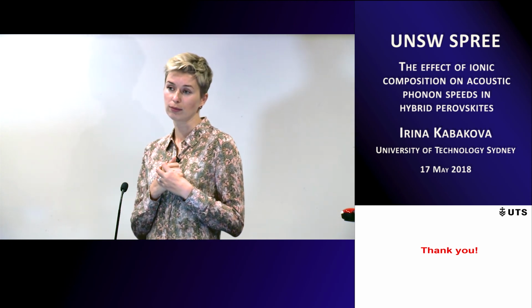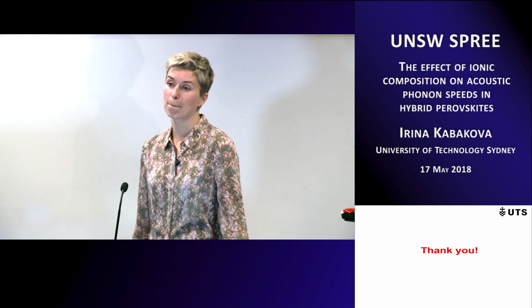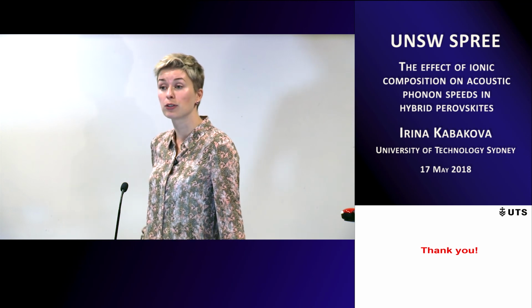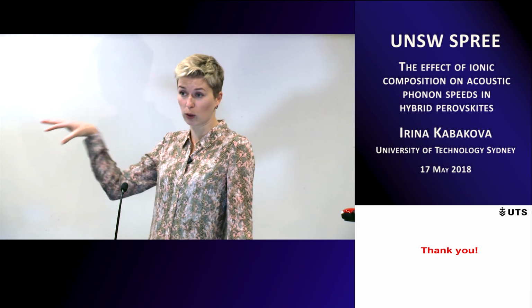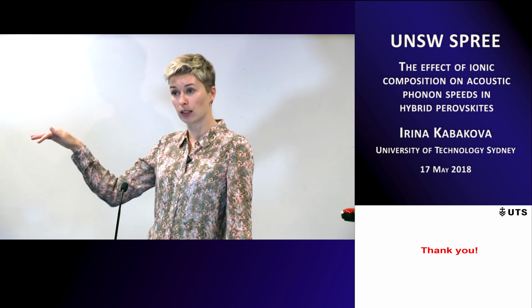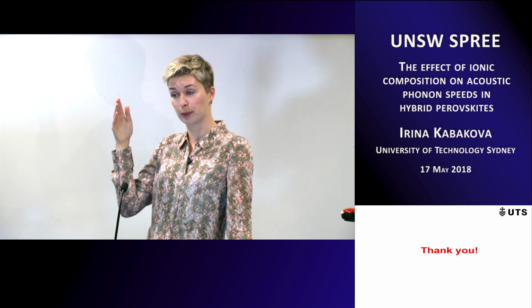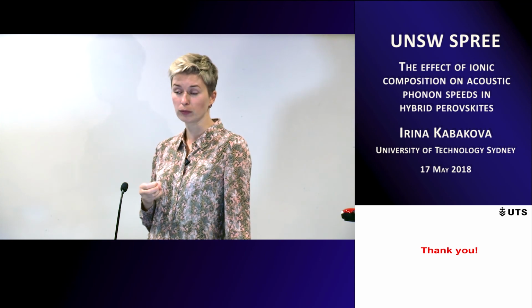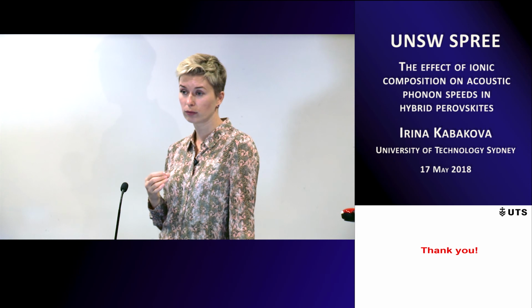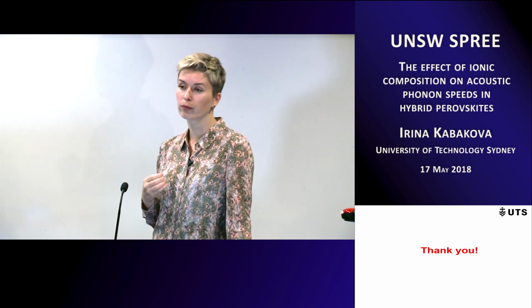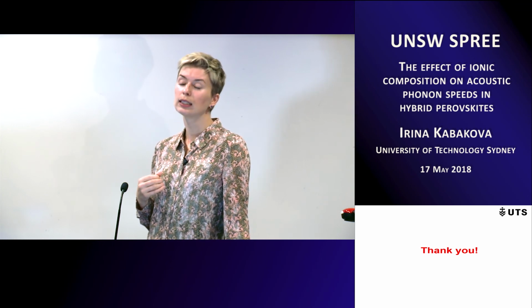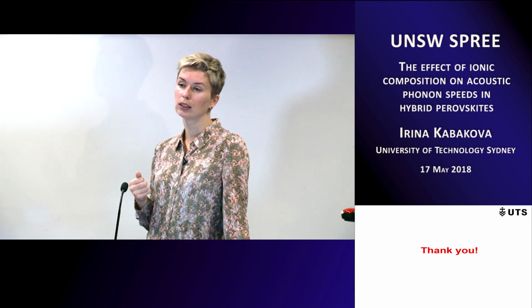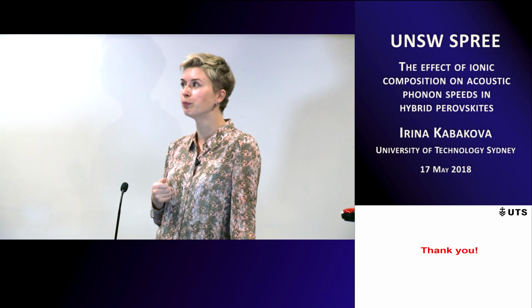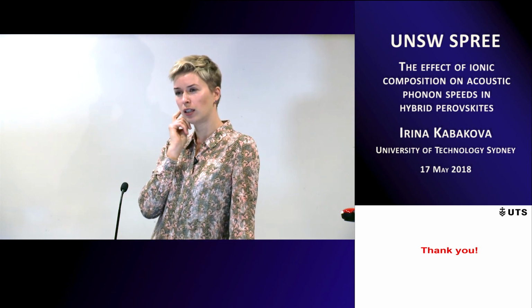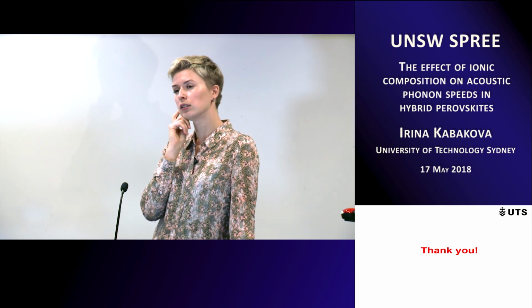Because iodide is not a cubic structure. Yes, but that's not the problem. The reconstruction equations will be somewhat more complex, but provided you know the axis, how you send light and collect your acoustic wave information, then you can still do spectroscopy. Another question: I know you need to have a proper alignment, so a single crystal is very important for this measurement. Yes. Is it possible to measure a thin film? A thin film will have domains of different symmetry. Now, the high quality thin films have a sort of preferred orientation.